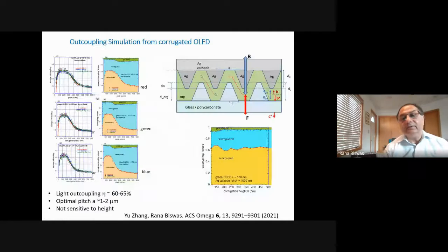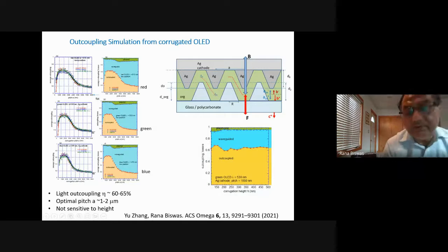So the structure that we developed experimentally is very much like the one you're looking at here on the right. You have a glass, it's actually a polycarbonate structure, and you saw the template of nanocones on that structure in the previous view graph. And on that, we spin coat the organic layer so that grows in a conformal pattern. And you have the HTL and then the ETL. And the boundary of that is the emissive layer, which I'm kind of showing you in this red over here. And then on the top, you have the silver cathode, and that also becomes a conformal structure. So these are the cones.